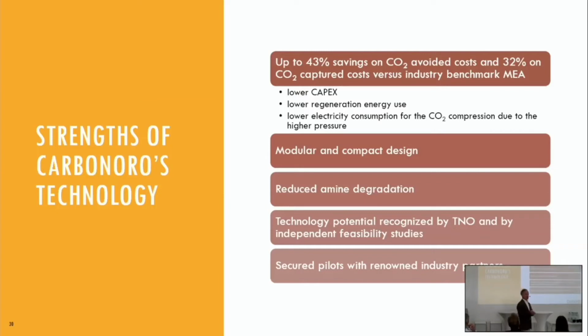We have done a feasibility study last year for another industry, in fact a hydrogen plant of a big chemical producer, and it showed that our solvent is about 32% more efficient in cost than the typical MEA solvent, and it's even further improved if you count the savings from the higher pressure, so also saving on compression and liquefaction of CO2. The origin of that is, one, the lower capex. Our solvent can contain slightly more CO2 than the traditional MEA solvent can, so we need less solvent and also smaller pumps and smaller installations. Secondly, it's the energy consumption, and thirdly, it's the CO2 that is produced at elevated pressure.